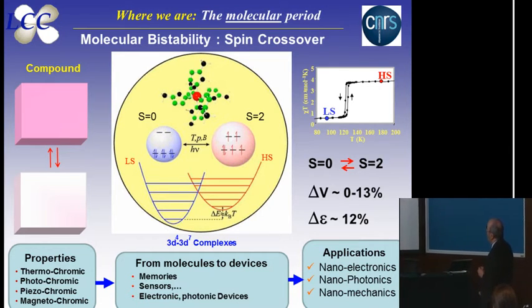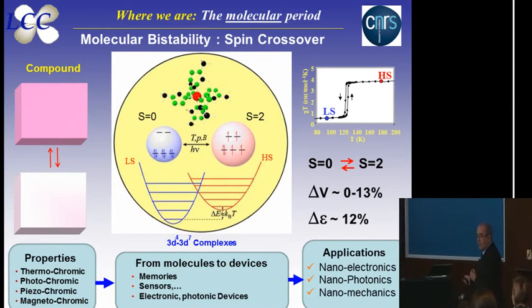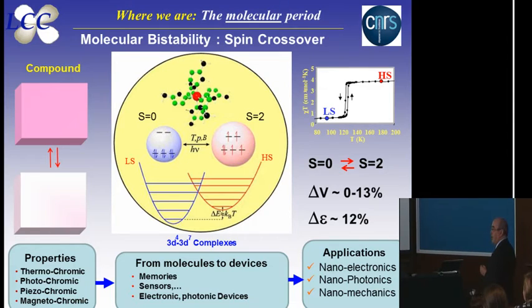Why? Because when you go from this spin state of the ion to this one, here you are populating the antibonding orbitals. And then the volume of the molecule is bigger when it's in the high spin form than in the low spin form. And then you can see a change of the volume of the molecule by 13%. That means that if you can control the switching of the molecule by light, temperature, or magnetic field, you can control the switch of its volume and then mechanical properties. And also because you are going from the low spin state to the high spin state, where you have two different electronic levels and vibrational levels, you can also see a change of the dielectric properties of the systems by around 12% when you go from one state to the other one.